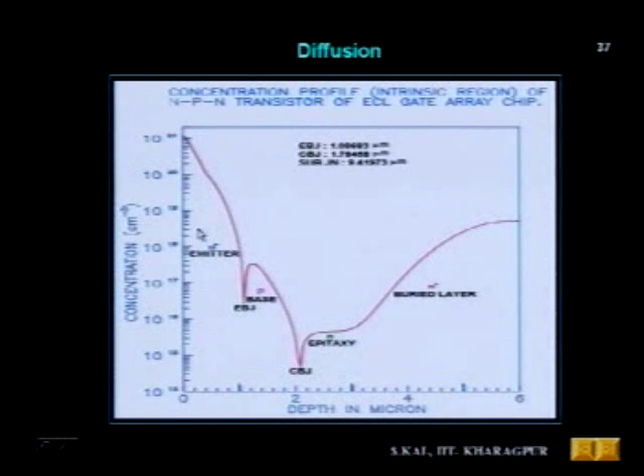This is the doping concentration. You see here the surface doping concentration is 10 to the power 21, that is the phosphorus doping, and this is of the order of 5 into 10 to the power 17. This is the peak base doping, and in epitaxy that doping concentration is very close to 5 or 6 into 10 to the power 15. That is the epitaxy doping. There is uniform doping, and the buried layer has become widened because of the out diffusion and impurity redistribution, and this buried layer peak concentration is again of the order of 5 into 10 to the power 18 to 10 to the power 19 in that range.